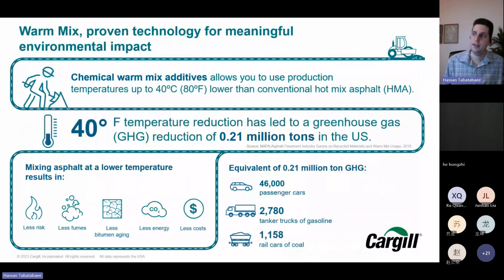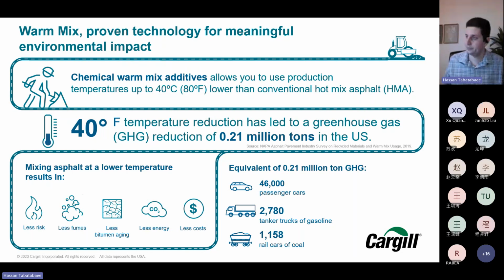And looking at that, it's estimated that in the U.S. alone, if a 40-degree Fahrenheit reduction in temperature was implemented using warm mix additive, about 0.2 million tons of GHG would be reduced, which is equivalent to taking 46,000 cars off of the road, or reducing about 1,000 rail cars of coal. These can start making a difference.